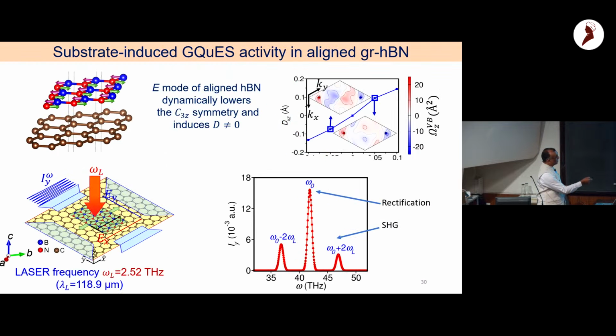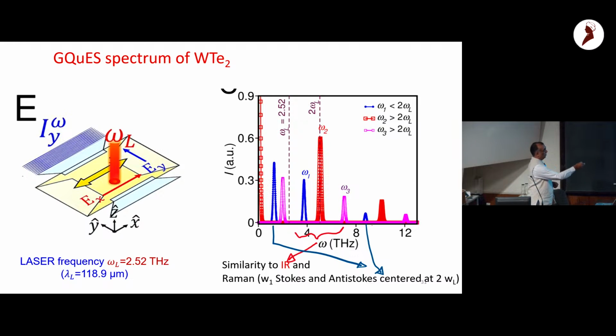We use these ideas now in WTe2. You have laser light at the same frequency, 2.52 terahertz, and you have tungsten telluride. You will see there are many peaks coming up now in the spectrum, and basically these 3 peaks are omega 1, omega 2, omega 3. These are the quantum geometry active phonons of monolayer WTe2, and they are like the infrared mode spectroscopy. But associated with them are also Stokes, anti-Stokes, similar to Raman, and those have also been pointed out. So we believe that this spectroscopy is actually quite powerful because it captures not only complementary information, it captures these 3 spectroscopies, Brillouin, Raman, and IR spectroscopies in one go. And I mean, if successful, of course.